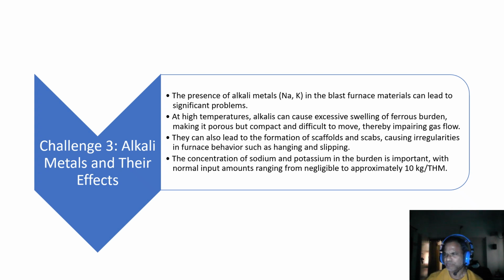Now, beyond physical properties, chemical impurities pose a significant challenge. The presence of alkali metal, particularly sodium and potassium, in blast furnace material can lead to subsequent operational problems. At the highest temperature found within the furnace, this alkali metal can cause excessive swelling of the ferrous burden. This makes the material porous but also compact and difficult to move, thereby